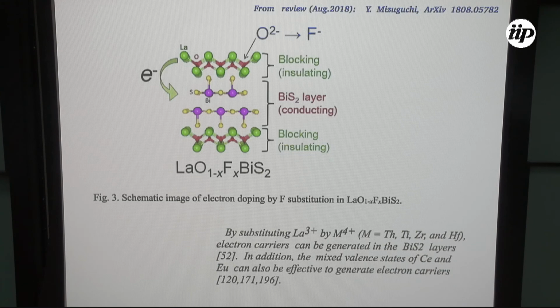Well, this is just a very pictorial view of the kind of doping I was mentioning. In the blocking layers, you have the oxygen, and you can just change one oxygen by a fluoride, and then you free one electron, which goes to the conduction planes. And so that's a way to dope with electrons those planes. And there have been many other studies of other substitutions.